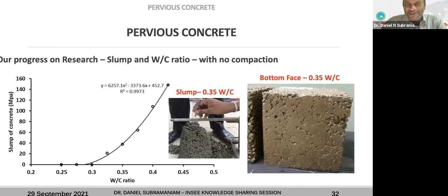So, an important one. This is what I have been talking about earlier. Slump has to be 0. Here you can see the trend. If you look at this plot, the slump is 0, and then after that, the slump is increasing exponentially. And I have shown 2 different things in this one: the slump at 0.35 water cement ratio and the bottom face.